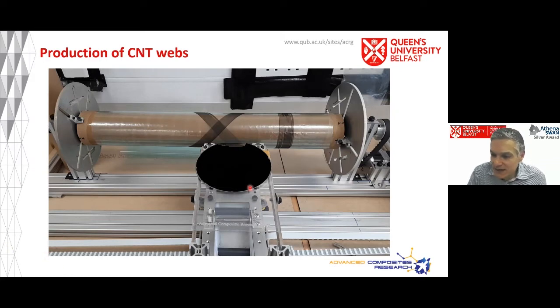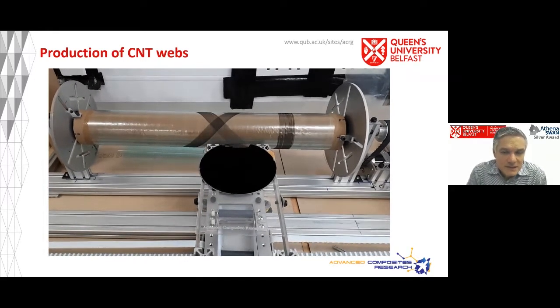the X winder here, if I can get the video going, hopefully. For some reason that's not going, but we've got the silicon wafer here again, and we are drawing the carbon nanotubes on this winder, and as it rotates, it draws the carbon nanotubes out. The reason why we've done this is that with the winding mechanism, we can alter the direction at which we wind those carbon nanotubes onto that surface. So that gives you something of the background. Oh, there we go, it's going now. So you can see how those carbon nanotubes are drawn very smoothly. The web is very regular.